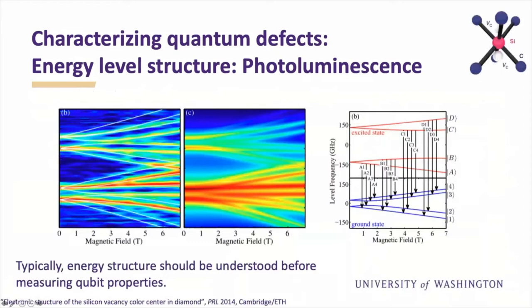Okay. Here's another beautiful example from about 5 years ago or so of the community working out the energy level structure, mainly using group theory, for the silicon vacancy center in diamond, which is another contender for network applications. And you can see nicely how if you know a little bit about the structure, and you take these measurements, then you can really understand the energy level structure. We call it the Hamiltonian. And then in this particular case, this level one and this level two would be your qubit states.